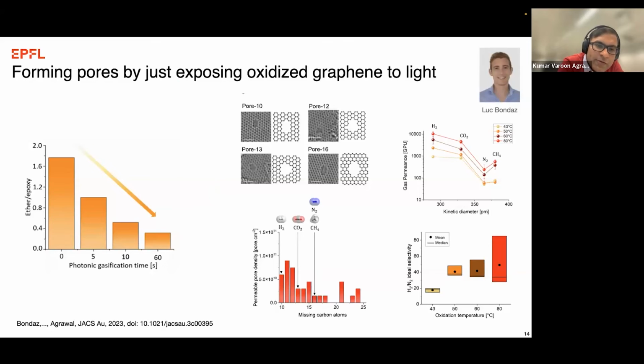All right. This is just to show that we can do this in many different ways. What I was showing before was by heating. We realized we can also do this by exposing graphene to simple light. So this is a 390 nanometer light, near ultraviolet, violet color light. And if you just expose it for a few seconds to this light, we start to form these holes. Right.